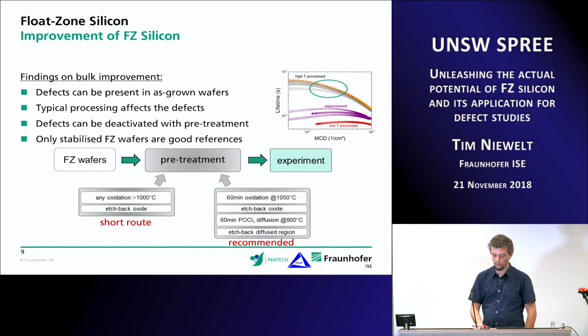The one that I would recommend, because it's giving the best results for us, is to combine an oxidation treatment at 1050 degrees with a POCl3 diffusion and an etch back that also helps you get rid of impurities that might be in the material or that you might have caught during the oxidation, for example.